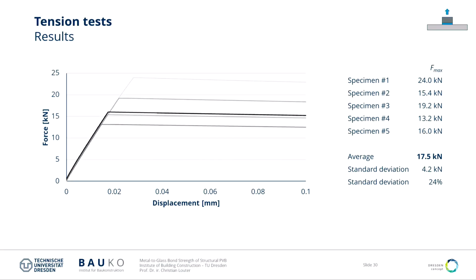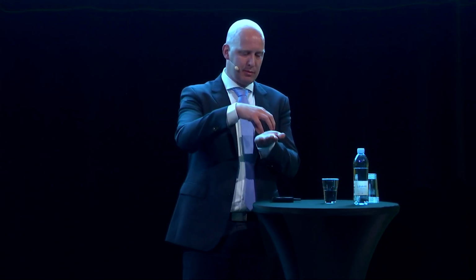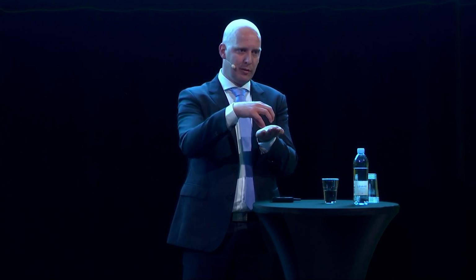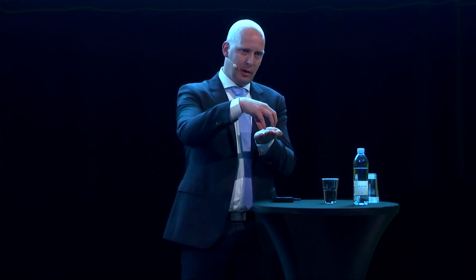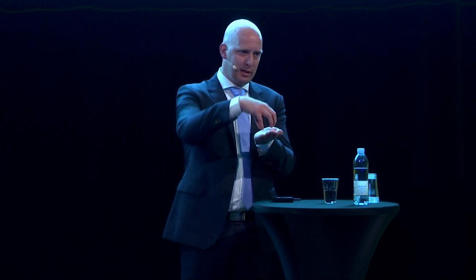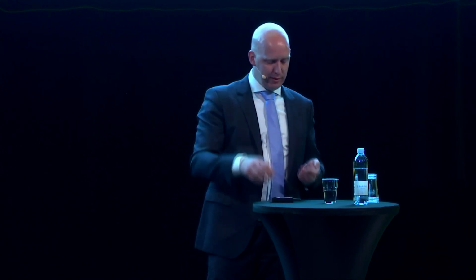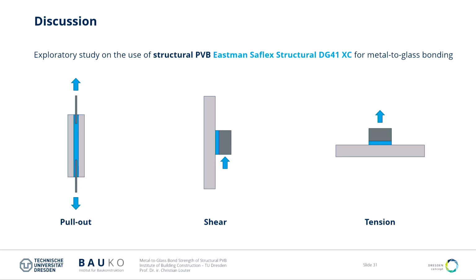In this case, we had quite a high scatter of 24% standard deviation, and we think that's mainly because there was some inclination of the button on the glass. So then you are not pulling it evenly, so you have a specific stress concentration from which the failure will start. So we have investigated these 3 options with this structural PVB.